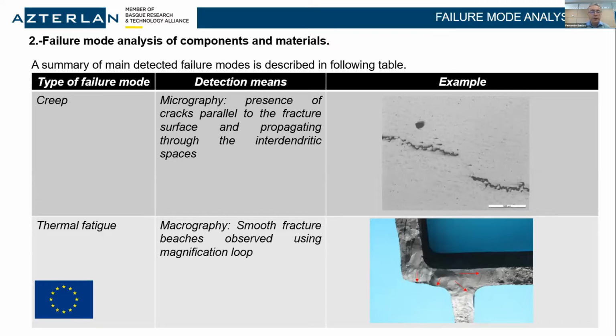For example, this is a brief example of how we identify the failure mode. Let's situate ourselves in the furnace that is working with loads on components, and they are suffering continuous loads at high temperature. This generates creep. How do we identify creep? Well, creep normally we identify it by means of micrography. If we observe quite clearly that there are cracks parallel to the fracture surface and propagating through the interdendritic spaces, it is clearly creep. So this is an example. You can see the metallography. You can see the cracks, and they are moving through interdendritic spaces.